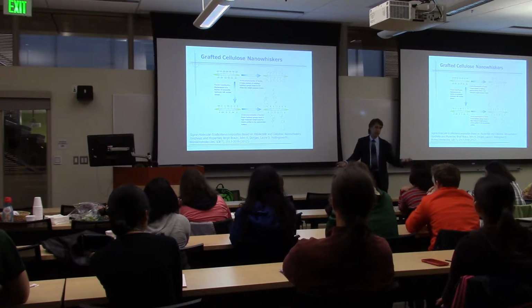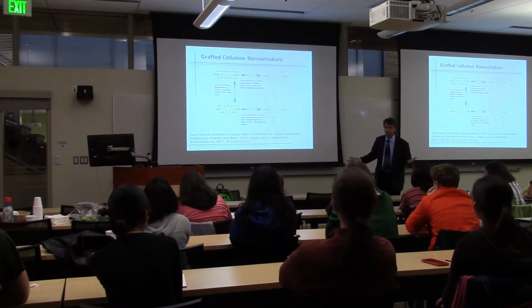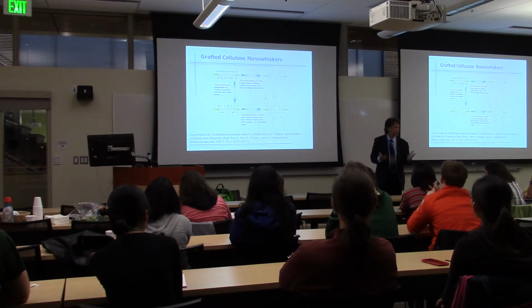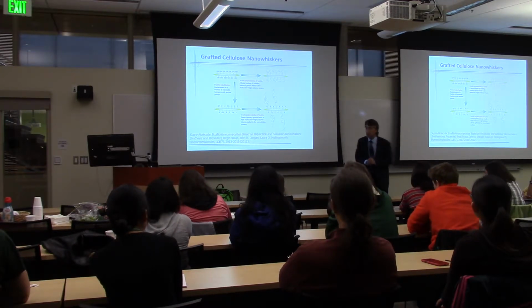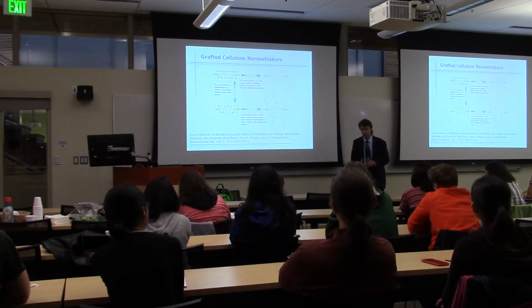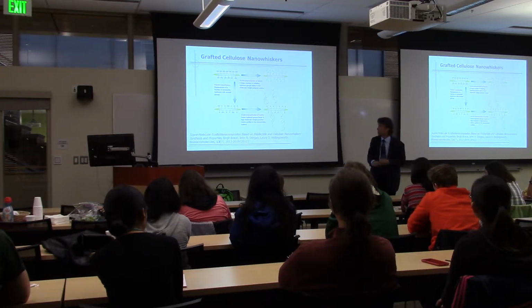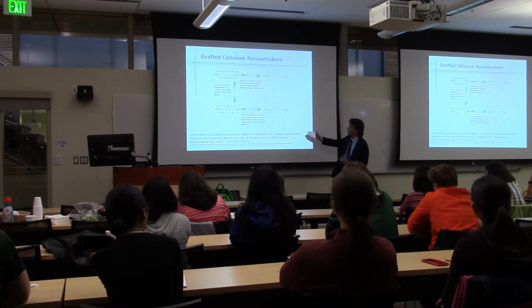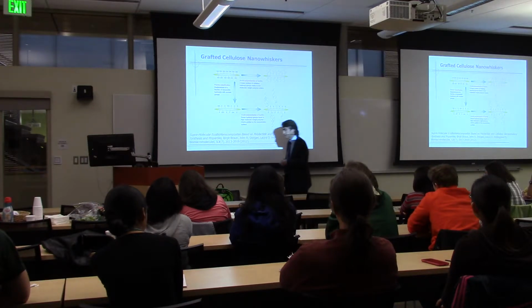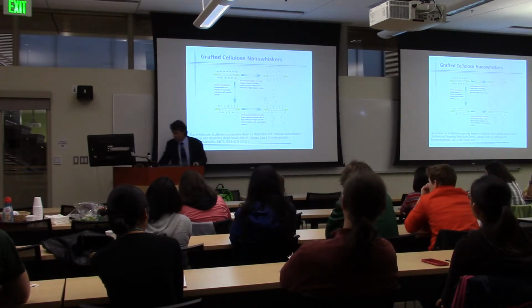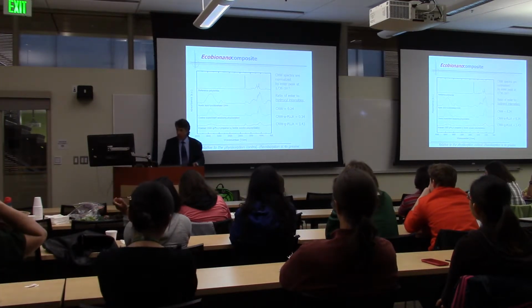And so, of course, we were making cruddy polymer, crumbly polymer would be a better explanation of it. It's just low molecular weight. But now we really had all the tools in place. We'd characterized the nanocellulose, we know how to control the surface chemistry, and we can actually dial in how many initiator groups should I have in order to really get a high molecular weight material. And so we were able to do that and grow some very interesting materials.